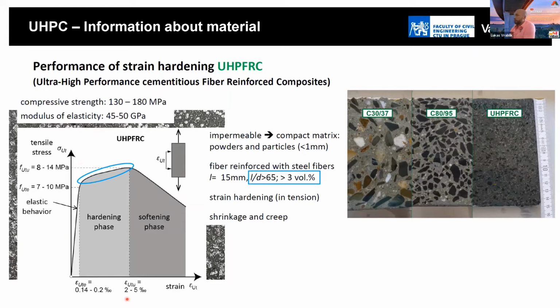Very important, the effect of the shrinkage and creep is very low, so it could be neglected. Only during the casting do you have to take into account the effect of the drying shrinkage, for example due to the shortening of the element. If you produce special elements or precast elements, you have to take into account this phenomenon, for example, to increase the length of the elements a little bit because of the shrinkage.